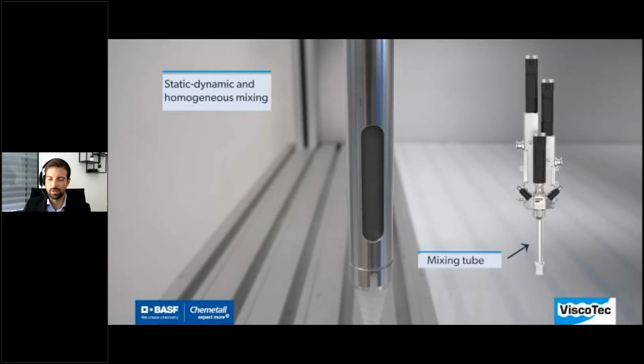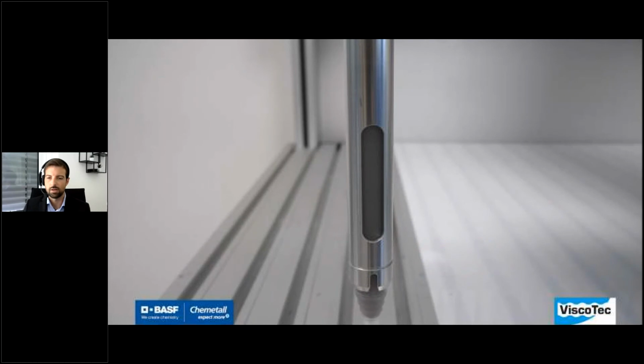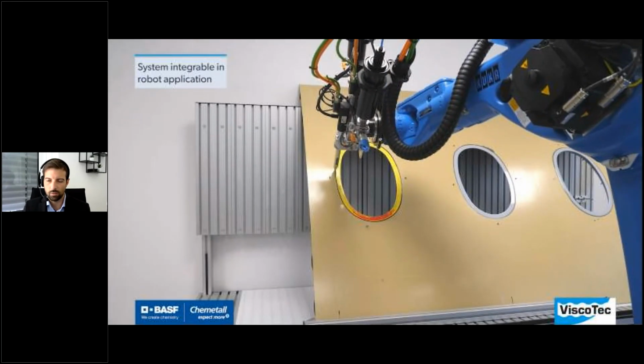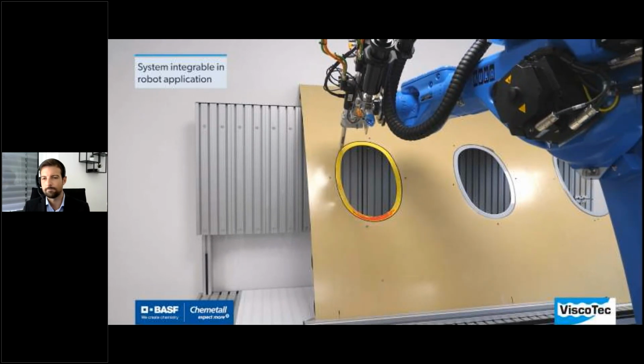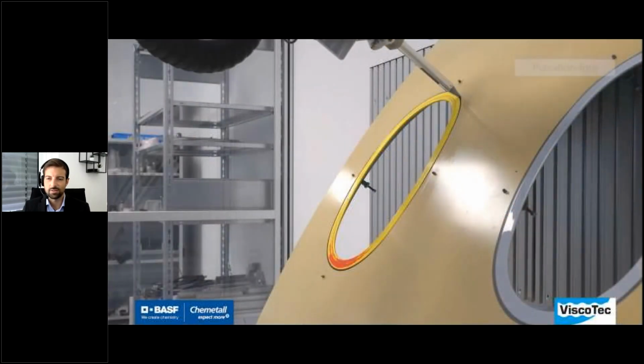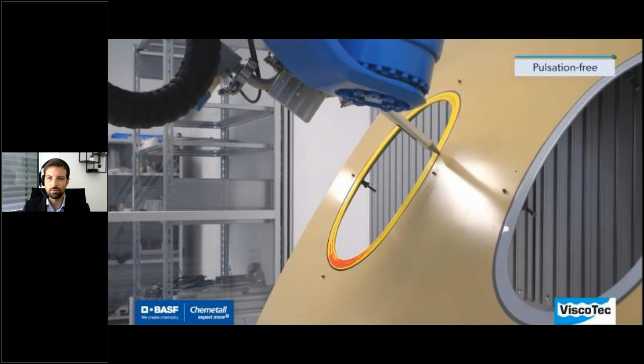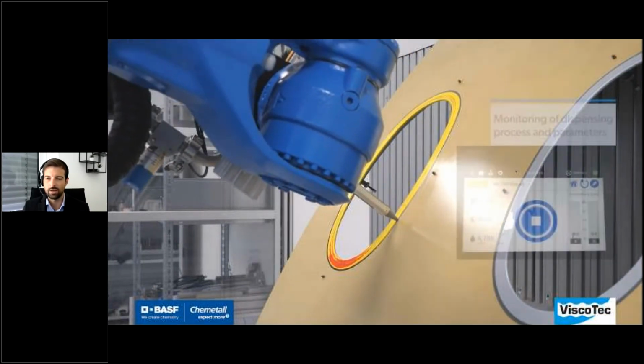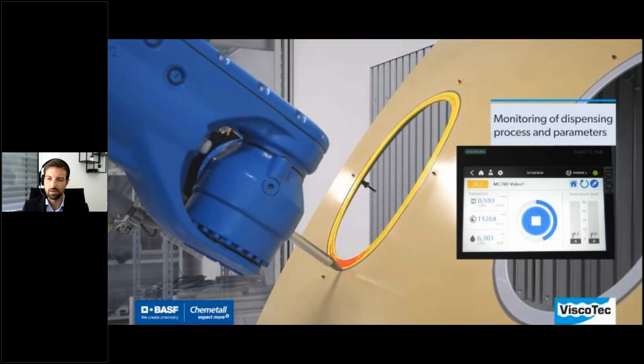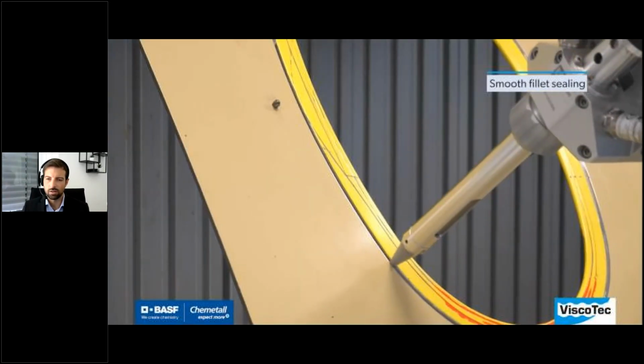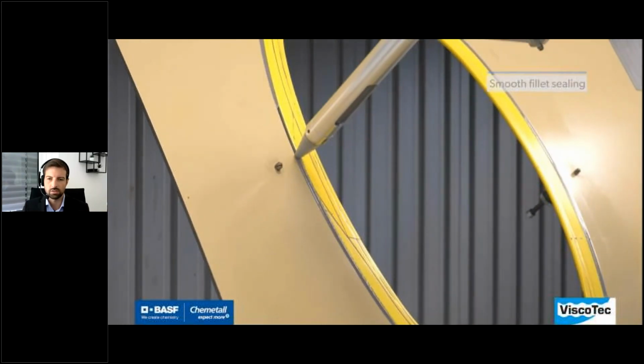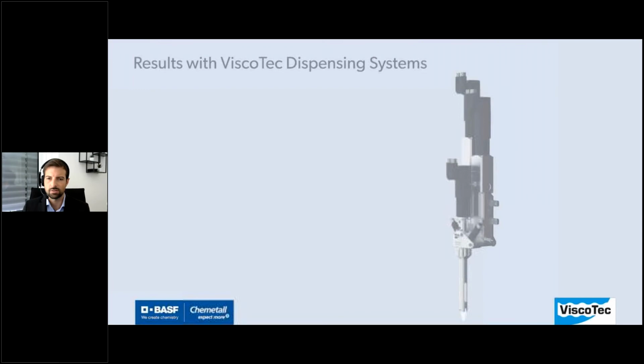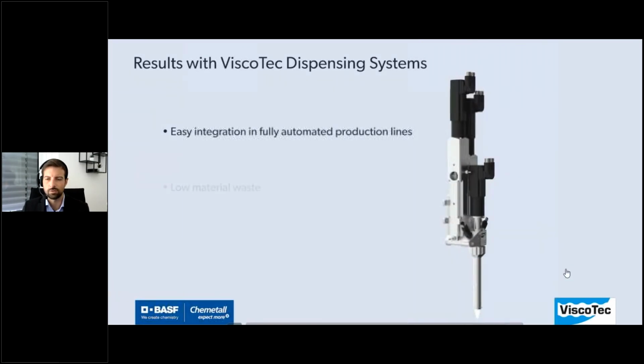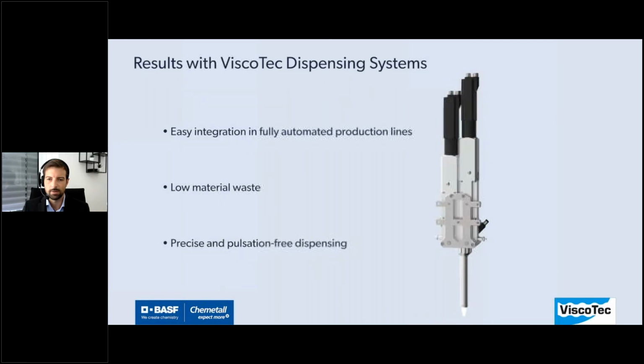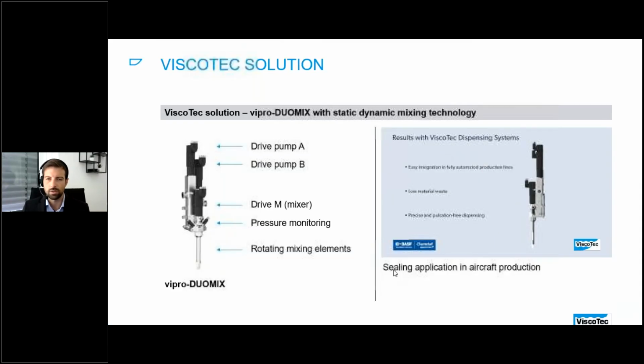Here you can see the rotating mixing elements, and the material gets conveyed and mixed until the outlet of the static mixer. And now we are able to conduct applications fully automated compared to many years ago where it was conducted manually by hand. So you don't have to mask the parts to avoid material distribution. You don't have to mix small cartridges in advance, since you're now able to use large pails or buckets. And this is possible thanks to the vipro-DUOMIX static dynamic mixing technology. So we also have a low material waste because we don't need to mix it by hand.